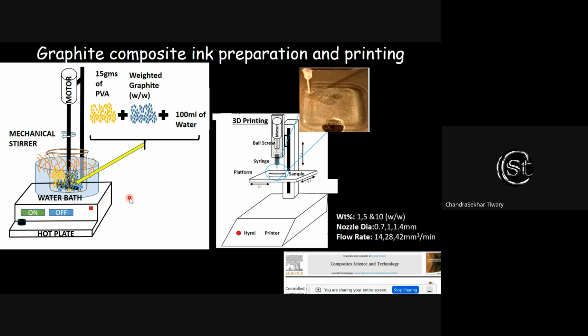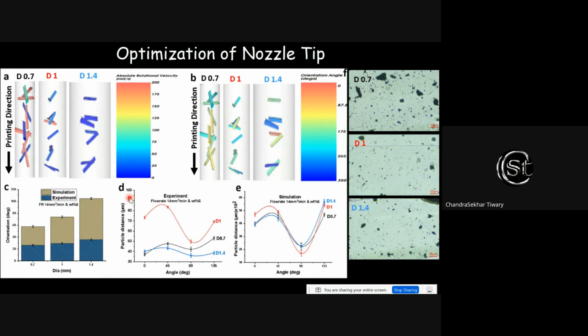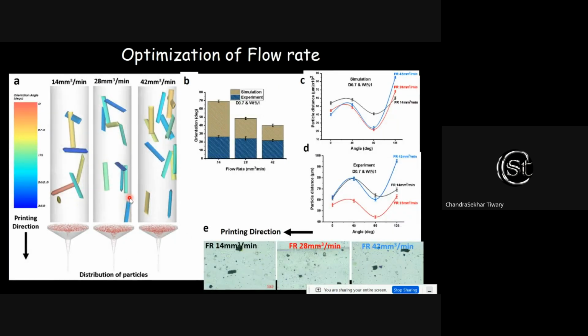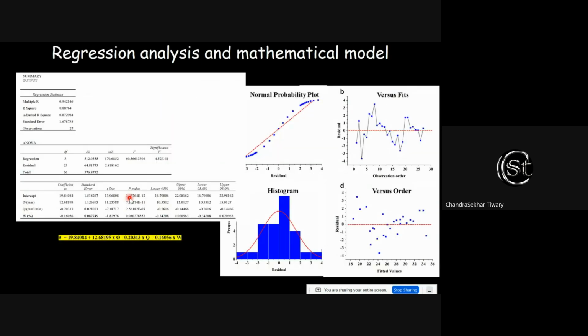We use graphite mixed with polymer and try to print them. Now, the interesting part is that if you use the right processing conditions, we can align these carbon or graphite particles in the polymer, and we can establish a relation between different processing conditions so that we get aligned fibers.